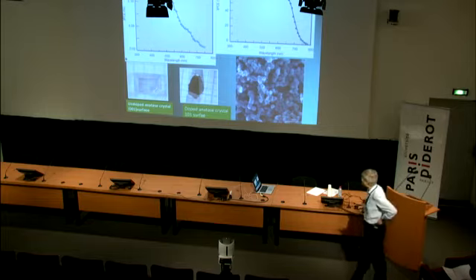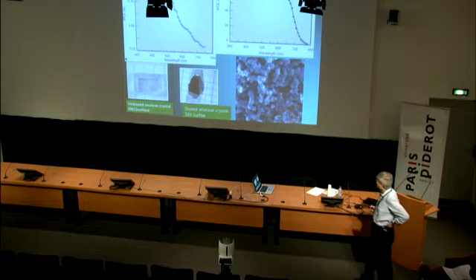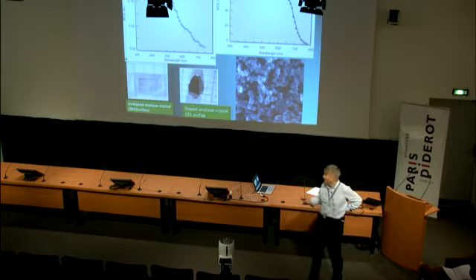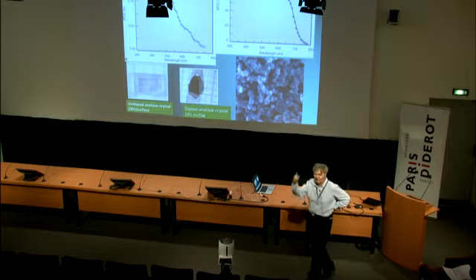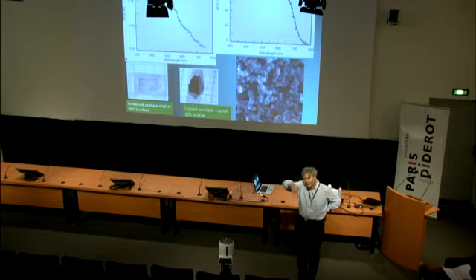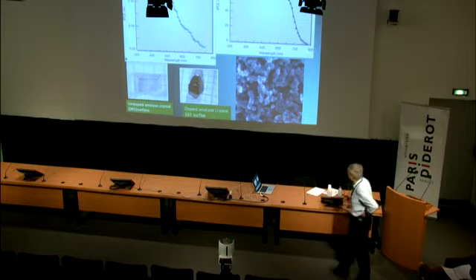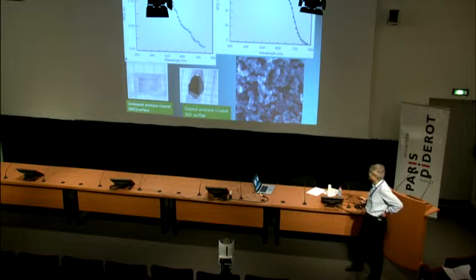You have to dope it and see what happens when you dope it. It turns black. And here's one of the problems: the interference of the black color comes from the conduction band electrons. It's the intraband excitation of conduction band electrons, and that produces quenching. So you don't have enough surface area, light isn't absorbed, you have the quenching. What comes out is a very poor device. The incident photon to current conversion efficiency is only 0.12%.